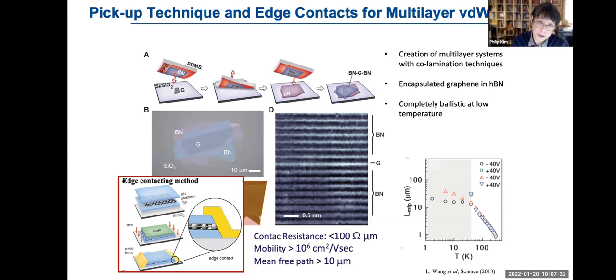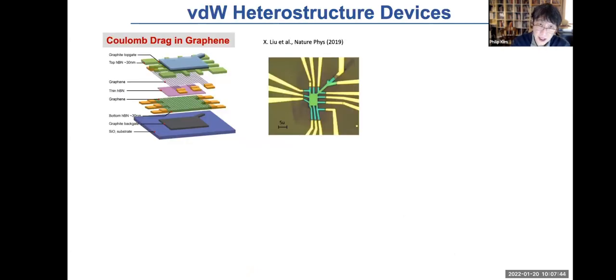This ability to create two-dimensional systems, especially in heterostructure form, immediately allows us to build rather complicated or interesting quantum devices. Here I'm showing you some examples. In this example, we have two graphene layers, bottom and top, separated by thin boron nitride. If you put in very thin boron nitride, it can serve as a tunneling barrier. If you put in reasonably thick boron nitride, a few nanometers, you cut out the tunneling, but you still have the Coulomb interaction between the electrons in the top and bottom layers that can create some sort of correlation between them and drive this system into a quantum mechanically unique state.